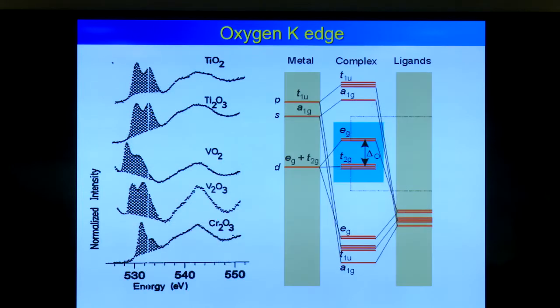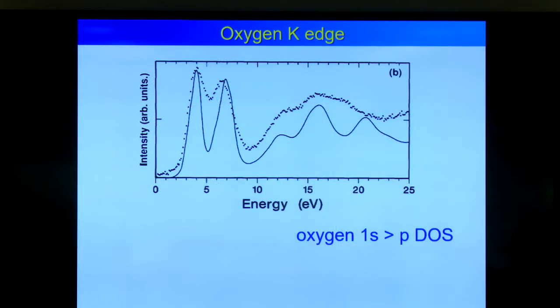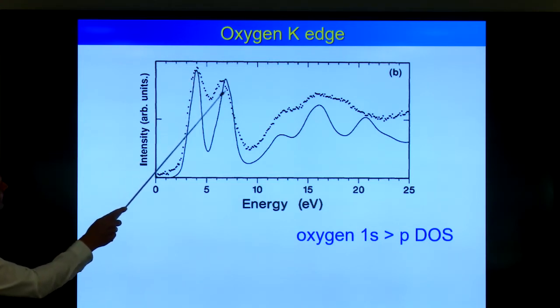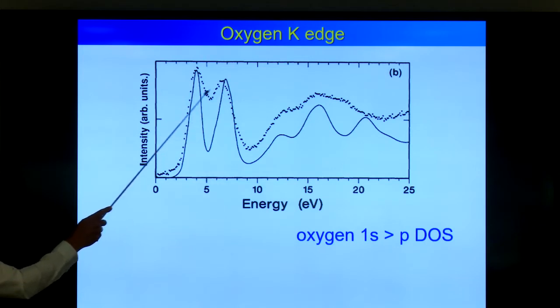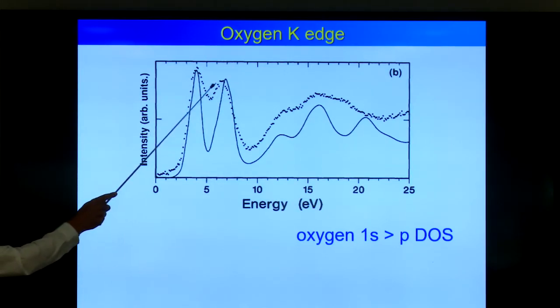So to go to real spectra, so these are the oxygen K edges of transition metal oxides. So you can see they are very old because they are drawn by hand. I didn't have a computer at that time. But this is a calculation without a core hole. But the interesting thing is that this is titanium oxide rutile, and in that case, if you put a core hole, so then I can point that out. So later we did that. So you see that the crystal field splitting is a little bit too large in the calculations, and if you put a core hole, that exactly fixes it, so you get really the correct splitting between the t2g and eg states.